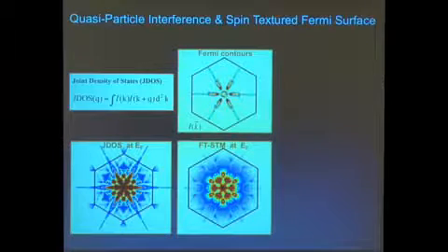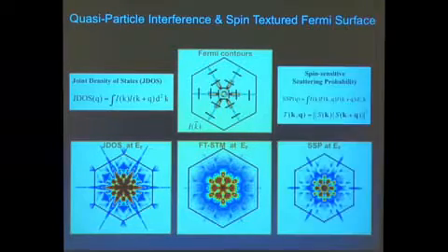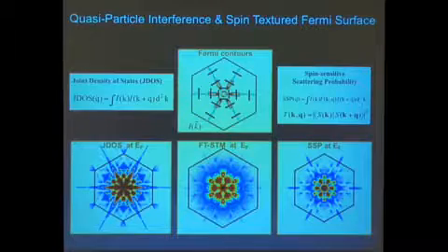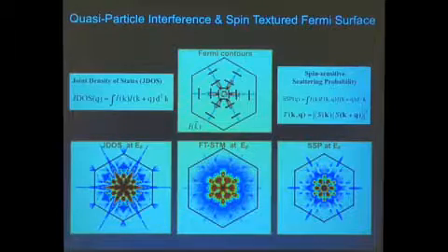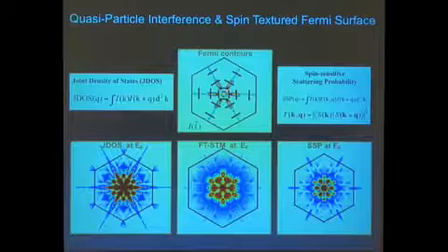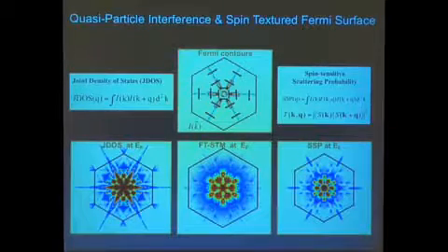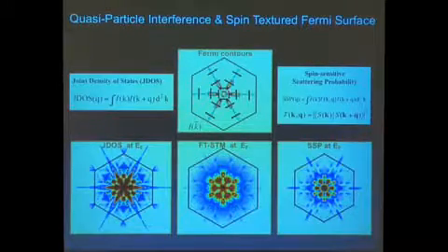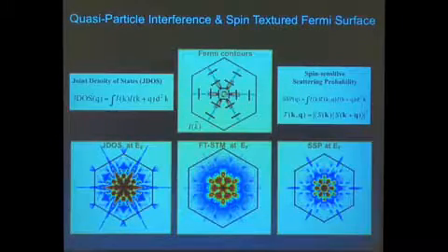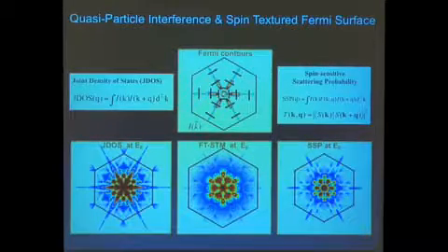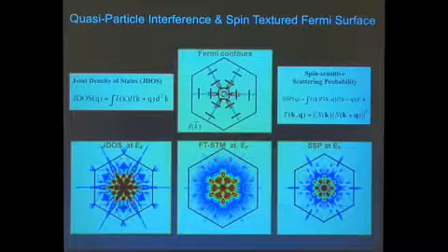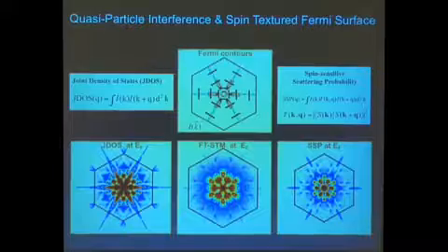And if you do that, this doesn't look that promising. There are some certainly connections having to do with crystalline symmetry, which is already here. But what you have forgotten to put in here is the fact that the electron's momentum and spin are locked together, which you can easily add in here. But this spin texture is actually quite special, because if you go from the center of the zone to the zone edge, basically you have a situation in which you have a handedness, if you like, to the material. There is one circling one way, the other way, and there is one left behind at the end of the day. So this is actually the definition of having a topological surface state. Otherwise, from spin-orbit coupling, you could just simply have an even number of those, and that would not be topological. Where does the radial dependence come from?